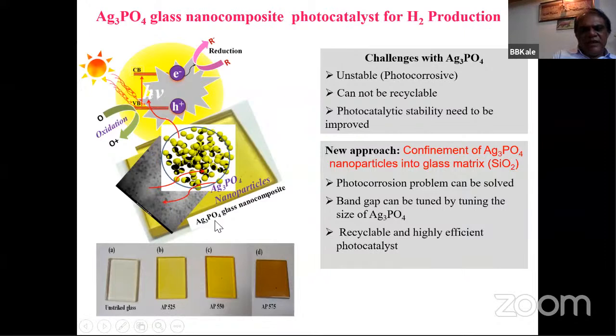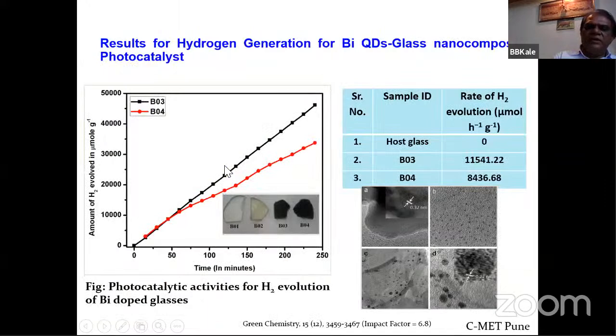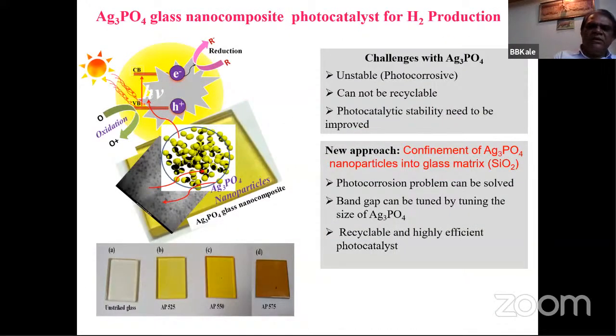This is the glass. In the glass, we develop silver phosphate nanocrystals. Silver phosphate is a very unstable compound. When you keep silver phosphate in the open, the silver immediately gets oxidized. If you stabilize it in glass, inside the glass we can see the particles here. This is a transmission electron microscope image I have shown you. It's very important, and the uniform color shows that there is a uniform distribution of nanoparticles. If you break the glass, anywhere you analyze you can see the same structure and same density.